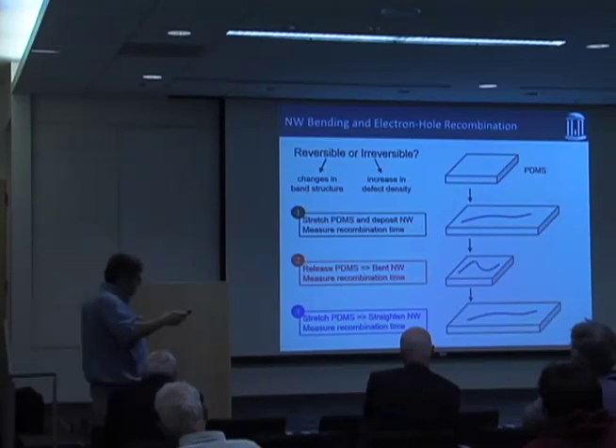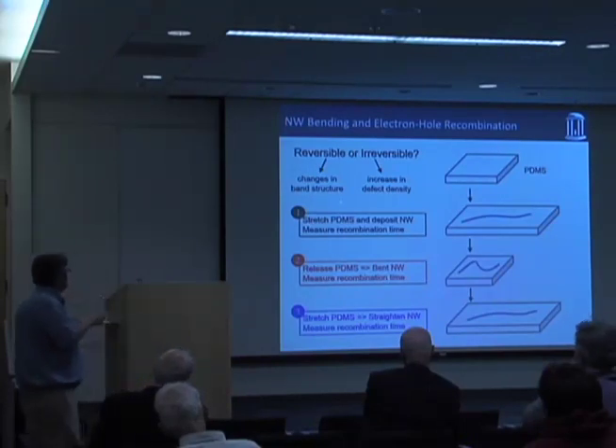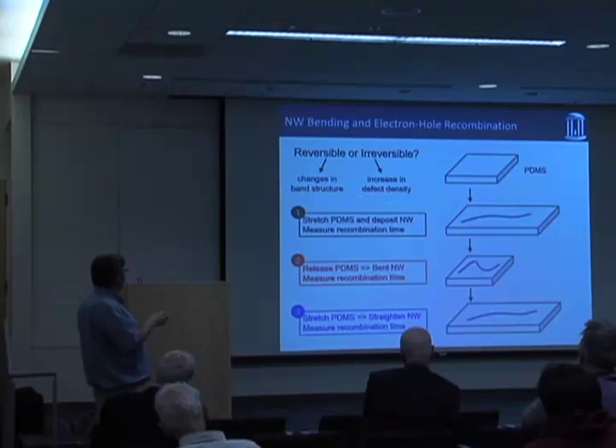If I took the nanowire and squished it up, or measured its electron-hole recombination, and then squished it up, and it got faster, and then stretched it back out again, it got slower. So if it's reversible, then perhaps that's telling me that it's changes in band structure. Because I figured that as soon as I introduce defects into that system, it would be hard to get rid of them.